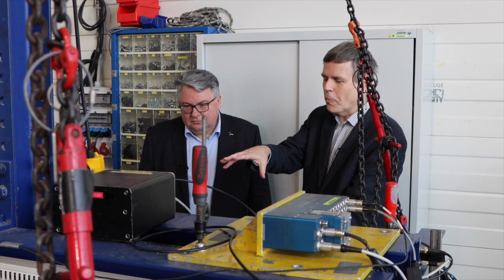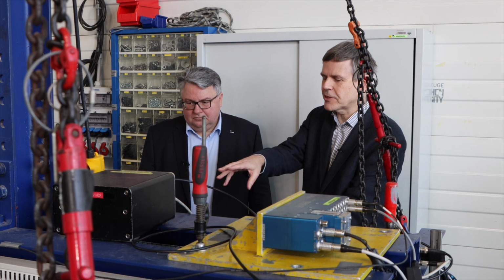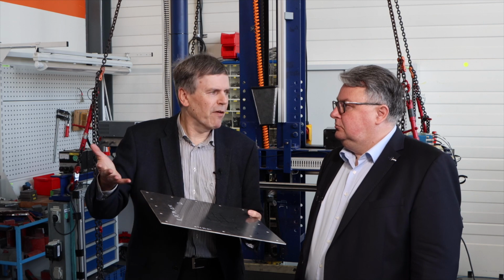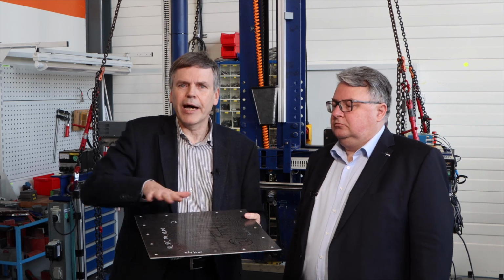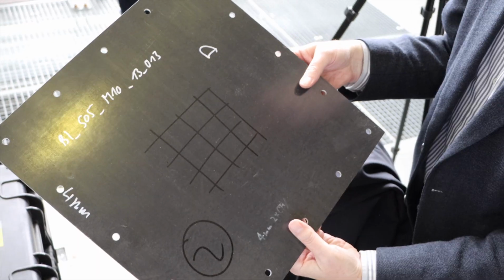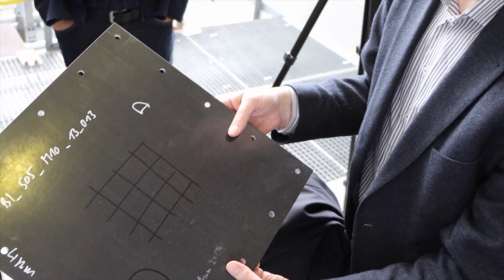This is several layers. This one is made from unidirectional tape that has typically a thickness of something like, it depends from manufacturer to manufacturer, but say 0.2 millimeter. This is a relatively thin plate, maybe only 4 millimeter. Typically plates would be maybe thicker, maybe 5 millimeter or 6 millimeter, but it's all about finding the right level of protection and the right layers with the right directions of the unidirectional tape layers.